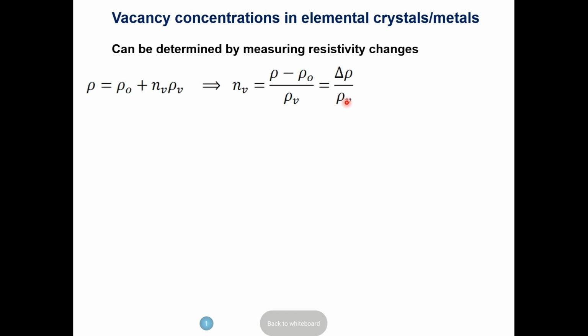And then you keep going. The math is simple: the fractional vacancy concentration is defined as the number of vacancies divided by the total number of sites. We know this has to come in the form with a temperature-independent part, as I showed on the previous slide, and a temperature-dependent part, that is the enthalpy. In that case, the delta change in electrical resistivity can still be given by that enthalpy term, but the prefactor A will be renormalized by a certain amount—this A has enthalpy, but it's still important.